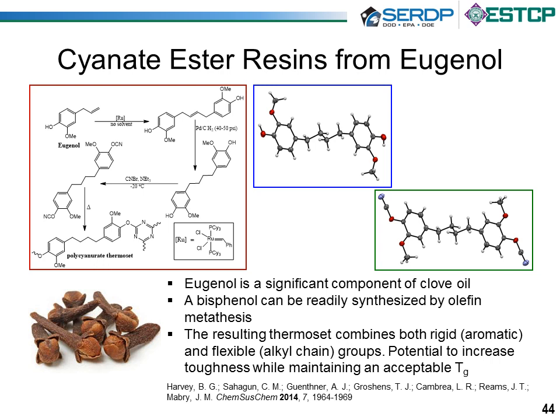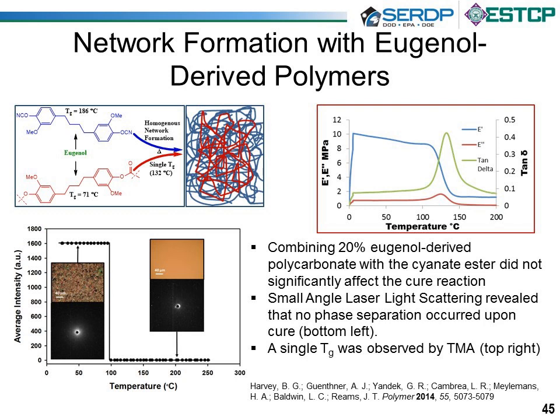So let's look at some of the properties. On the left, actually, we conceived of an idea where we'd do a blending study where we'd take the eugenol cyanate ester, which actually has a moderate glass transition temperature of 186 degrees C, and blend it with a polycarbonate that we also synthesized from eugenol that has a glass transition temperature of 71 degrees C. When we blended them together and cured them, we actually got a material that had a single glass transition temperature at 132 degrees C. If you look to the right, you can actually see thermomechanical analysis of a sample that shows a single glass transition temperature at 132 degrees C.